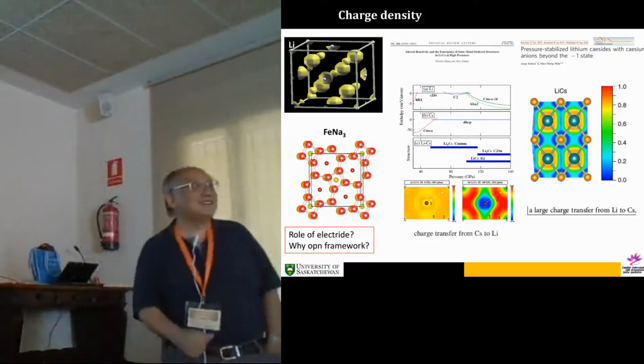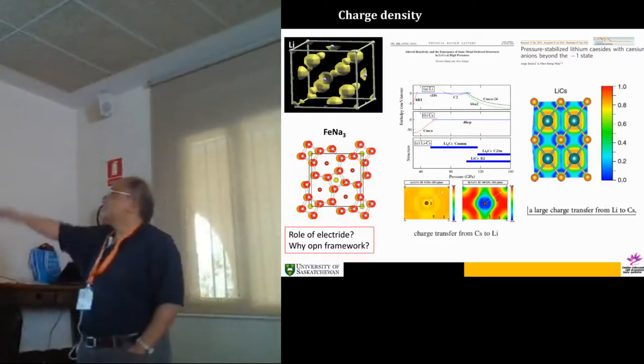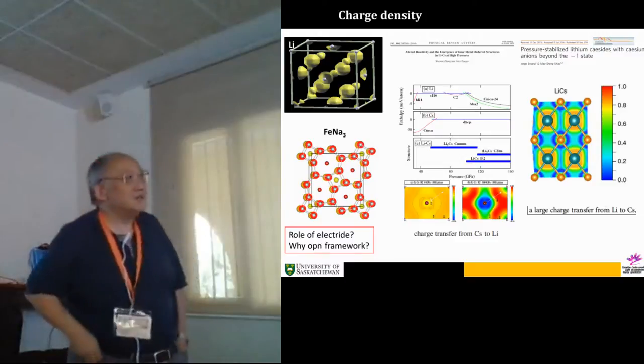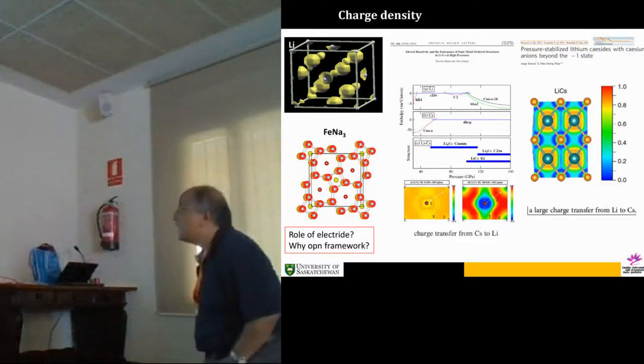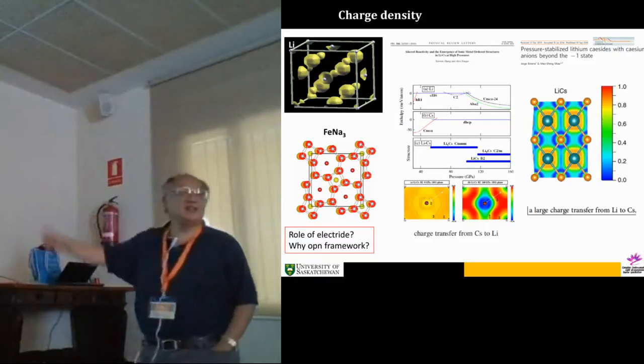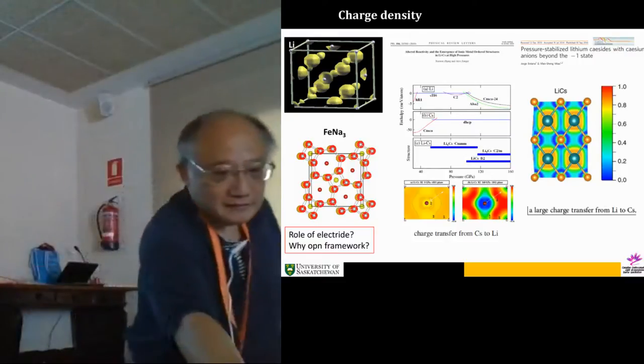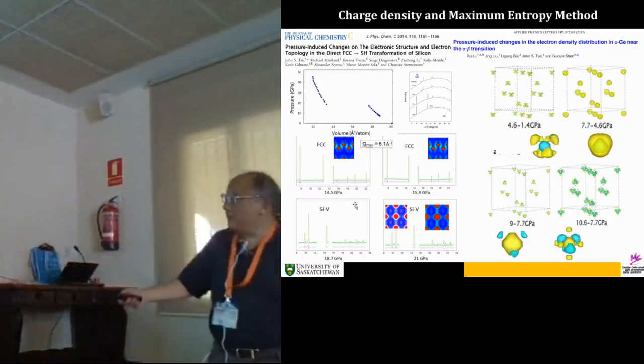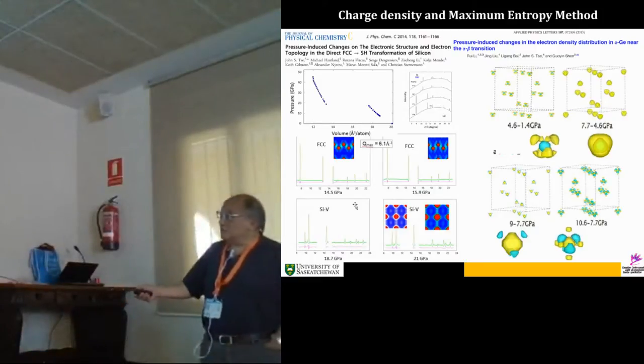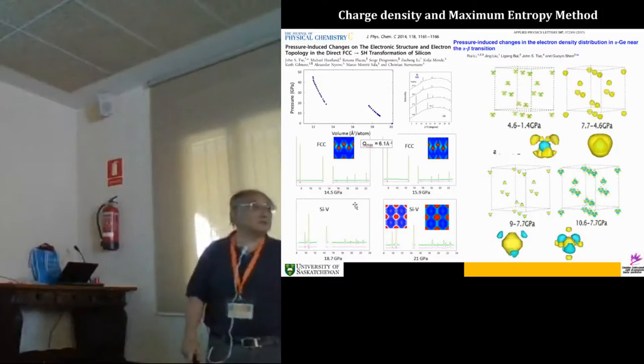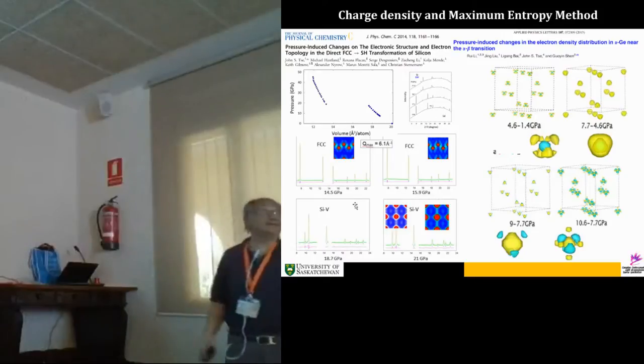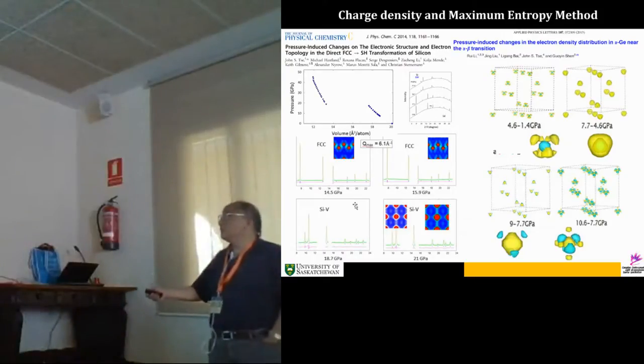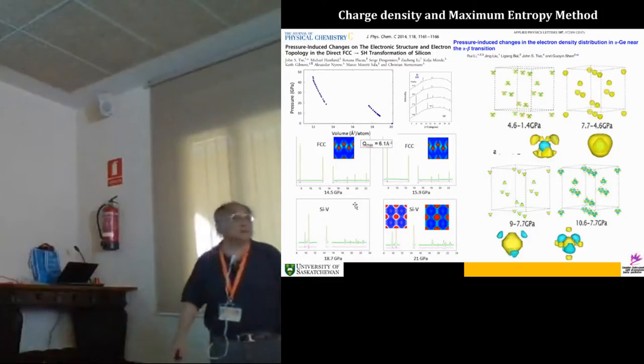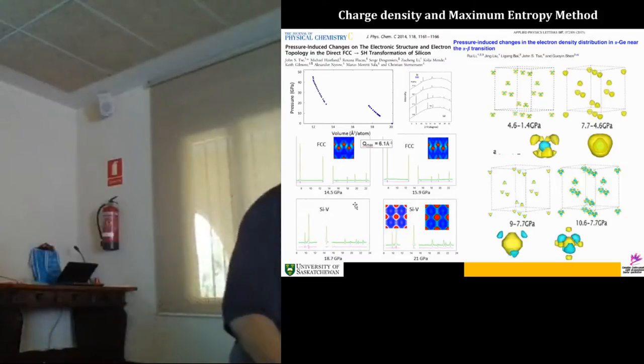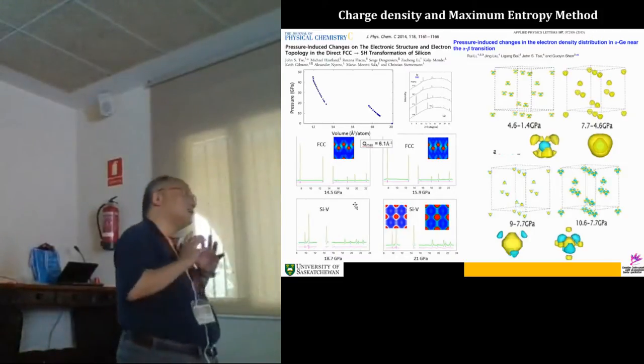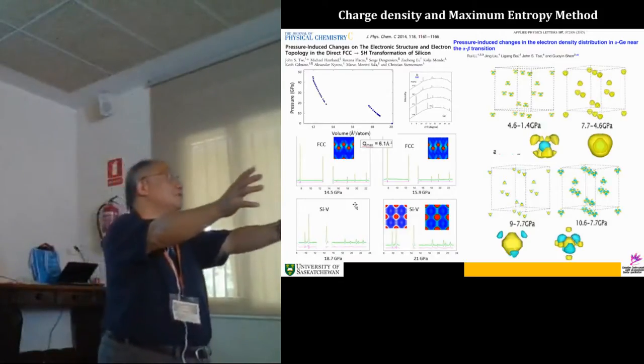Okay, theory. Everybody trusts theoreticians. This is a paper from two years ago, a prediction of lithium cesium. They say lithium cesium only exists at about 40, 50 or 60 GPa, in that graph there. All right? And this paper plots the electron density difference, and they see that the electrons are being transferred from the cesium to the lithium. There's a paper that came out last year in Nature Communications. They did the same thing. Without citing this paper, they say there is a large transfer from lithium to cesium. Now, that really is a very fundamental problem. It's not that they did the wrong calculation. It's a matter of how to define charge density when you're transferring electrons to the interstitial region. Where do you grab that density?